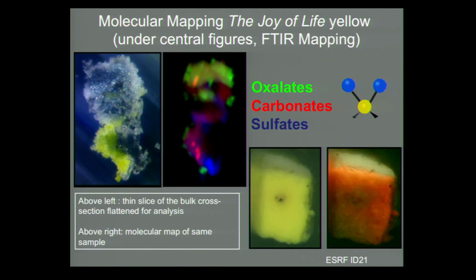And then we also used a synchrotron to do molecular mapping of this particular paint sample, which comes from underneath the central reclining figures. So this is the paint sample in visible light. This is the sample in ultraviolet light. And we took just a very thin slice off the front of this paint sample and then squashed it out flat so that infrared radiation could be transmitted through it. And we were able to get a molecular map of this little slice of the paint cross-section. And what you can see is that oxalates are concentrated in the white photodegraded layer. And so the oxalates are also a photodegradation product as well. They're not something that was added by the paint manufacturer. And we see the carbonates showing up below the oxalates, and then the sulfates again distributed throughout the entire paint layer.